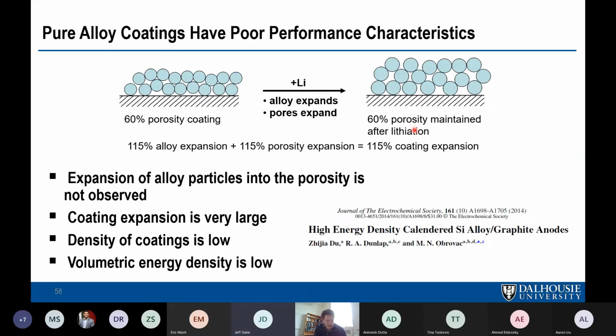Okay, and I think this is coming to the last point here, which is trying to make a coating with alloy materials. If you coat anything by hand in the lab and you measure the porosity, it's about 60% for any particles coated by hand. Maybe graphite, no, those are 60% too. They tend to be roundish. If you want to get lower porosity, you have to calender. And for alloy materials, it's very difficult to get this porosity out.